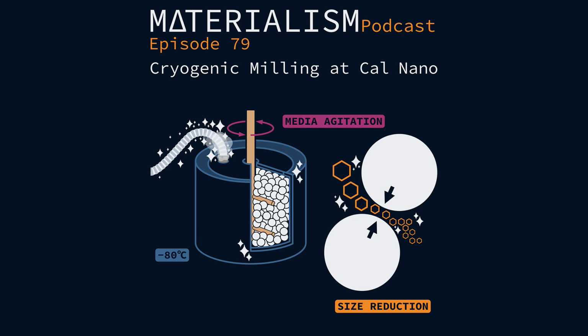And then another one, more on the particle size reduction, that we're working on is with a material for carbon sequestering. It's a material that starts off in these large beads, and they wanted to increase the surface area in order to have additional carbon absorption during their process. They couldn't have any sort of heat put in because it completely degrades the material. So we did it with cryomilling, worked like a charm, reduced the particle size, they get improved properties, and off to the races.